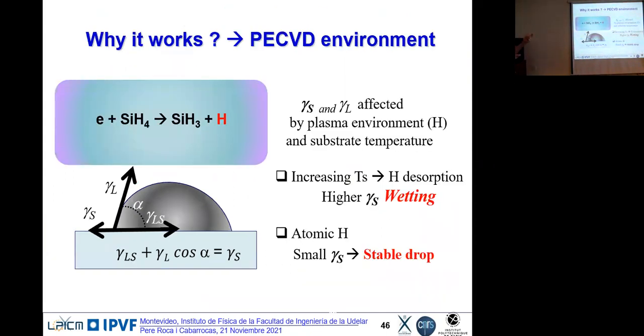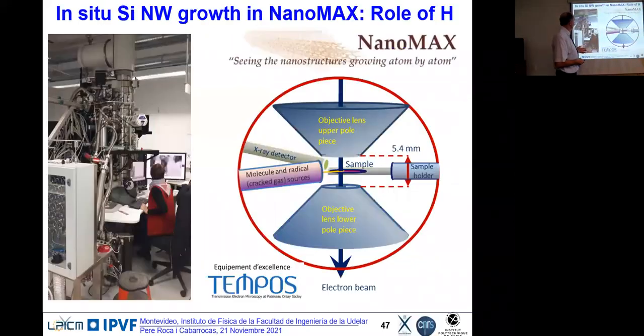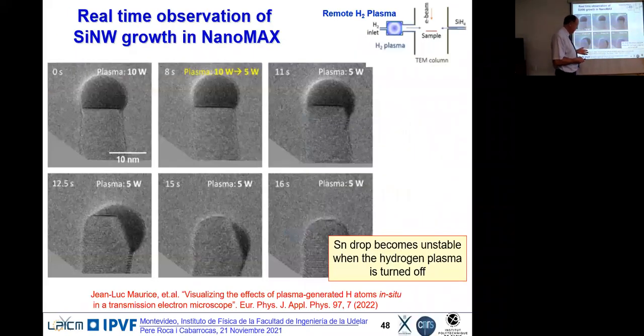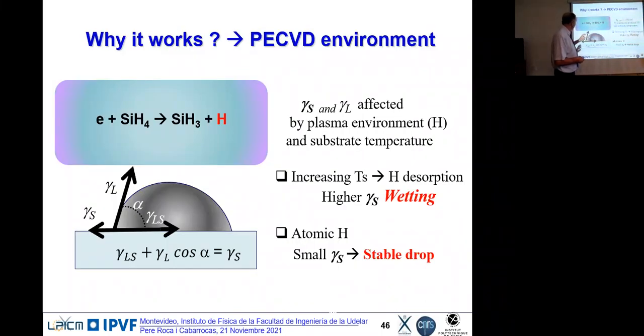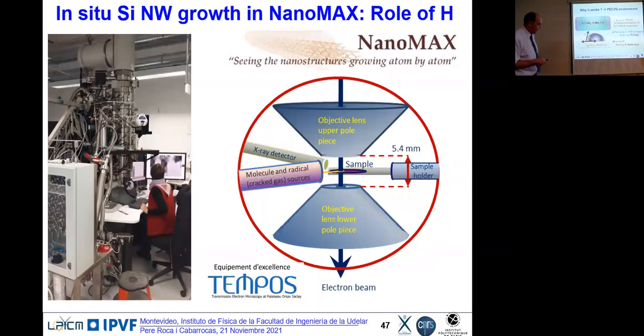Why does it? And okay, we do experiments. I am a stubborn experimentalist. Sorry. So I try, and I grow wires. So why do they grow? It grows because I am in a plasma environment. I have atomic hydrogen. And this atomic hydrogen can increase the surface energy here, or can decrease the surface energy by hydrogen passivating the surface of the substrate. And this is something that we could check using in situ TEM.